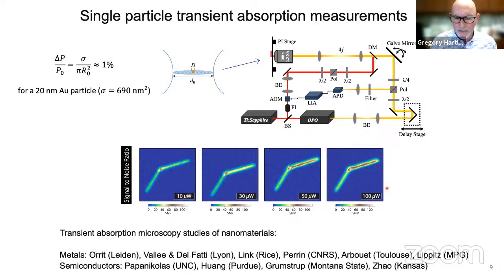These are actually the only images I'll show of some semiconductors. This is semiconductor nanowires made by my colleague Ken Kuno. These images were recorded by overlapping the pump and probe at the sample and then scanning the sample through the laser beam to make an image. The point of this experiment was that we recorded images at different powers of the probe. And when we do that, we see that signal to noise increases. And if you think about that a little bit, it means that you're shot noise limited. Okay, that the fluctuations of the laser are not determining the noise in the experiment, it's only how many photons you count. So if you have a very high frequency laser pulse and you count lots of photons, you can get enough signal to make an image and study the nano object.